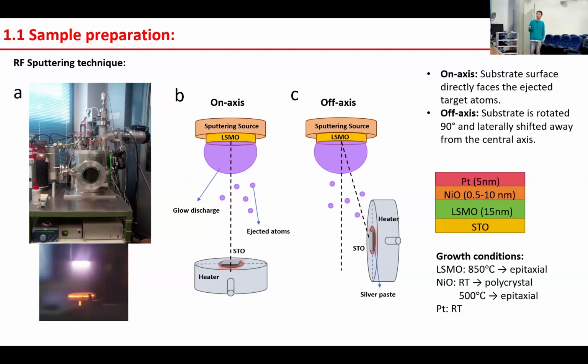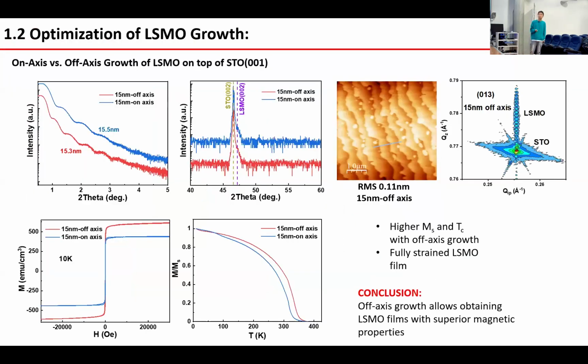For growth conditions, we utilize LSMO at 850 degrees, 500 degrees for the epitaxial growth, and then for the nickel oxide we choose room temperature for polycrystalline, and 500 degrees high temperature to achieve epitaxial growth. And the platinum we utilize at room temperature. So first, I will optimize the LSMO growth with on-axis and off-axis.